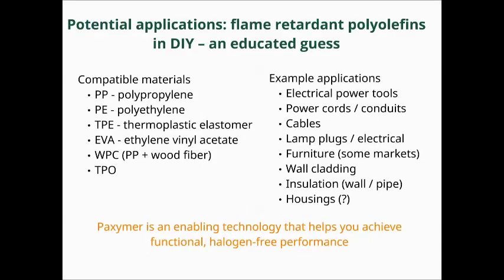I wanted to conclude my presentation by giving a little more technical detail about what types of materials we have experience with, and then I'm making a bit of an educated guess for the do-it-yourself or consumer markets, where you would expect to find flame retardants. If you look at compatible materials with the Paxymer technology, it's polyolefins. I mentioned that a couple of times. What does that mean? It's polypropylene, polyethylene, thermoplastic elastomers. They need to be olefinic based, but nonetheless, a lot of those. Ethylene vinyl acetate, also things such as WPC, wood polymer composite materials. These are typically polypropylene based, and then you add wood fiber from 30 to 70% depending on what you use them for, and also for TPOs.